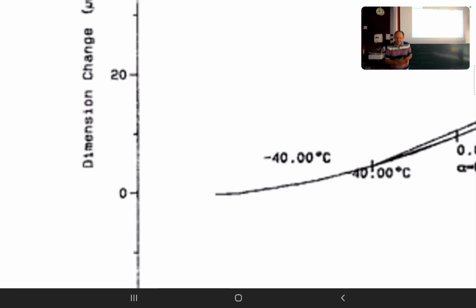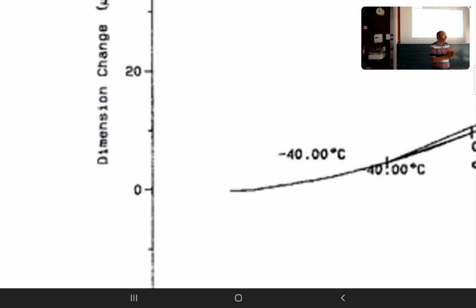Now let's have some other aspects of such adhesives. We already have seen the CTE measurement. In fact, we take a specimen of that, for instance, a small block of that material, and we put it in a thermal expansion tester. That's a so-called TMA, which is a thermal mechanical analyzer. In German, you also say dilatometer to measure thermal expansion. And you see we have a low slope, maybe here up to 50 degrees centigrade in that case, and a high slope above that glass transition.